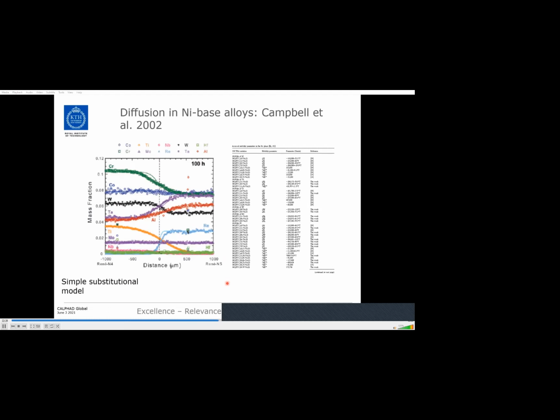So here is one example. It is a database for nickel-based alloys developed by Campbell and co-workers at NIST. And this shows a joint between two nickel-based alloys. And you can see that there are many alloying elements here. And they used a simple substitutional model for this alloy. This is in FCC phase. So we show here the concentration profiles of the different alloy elements. And here is the position of the initial joint.